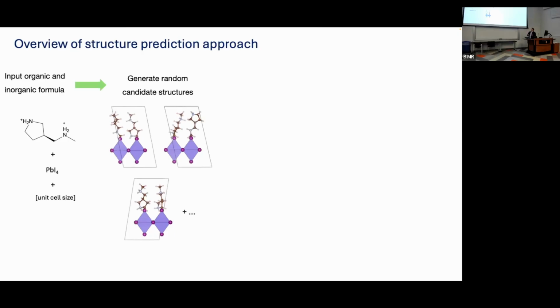And what we've focused on was treating the organic lattice part as a sort of ligand binding problem. So in ligand binding, you have some well-defined pocket or lattice slab, and you want to put the organic molecule in different permutations. For example, you can have different orientations of the organic molecule, or different angles relative to the surface. And these are all hand-coded. So we create a set of different possible stochastic operations. We have a list of ranges that we allowed. So the tilt angle could only go plus or minus 15 degrees, for example.